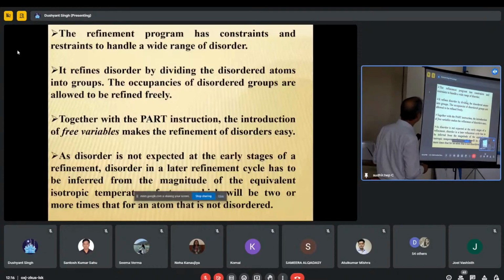The occupancy of the disorder groups is allowed to refine. We cannot keep the occupancy fixed, because normally in refinement we keep the occupancy as 1. Whenever we have to solve a disorder, we have to keep the occupancy free and allow it to refine. Maybe it is 70%, 30%, 20%, 80%. Unless you allow it to refine, your program will not run.